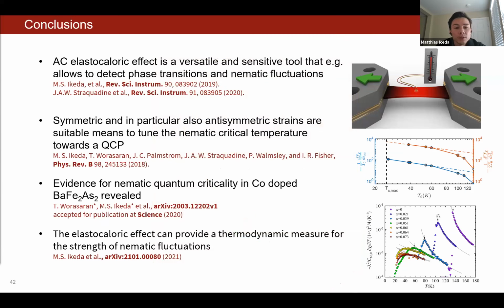And with this, I would like to come to my conclusions and really briefly go through the relevance of our findings. As was mentioned before, in the absence of the coupling of lattice and nematic degrees of freedom, nematic fluctuations are known from theoretical studies to promote superconductivity. But on the other hand, through theory, we also know that coupling to the lattice actually restricts the critical fluctuations. So what we have found is a wide regime governed by quantum critical fluctuations in the system. But we have also found that the coupling of nematic degrees of freedom and the lattice diminishes as we go towards optimally doped regions in the phase diagram. But at the same time, the coupling to the charge carriers increases drastically. And these are all the ingredients needed for nematic fluctuations actually being important for superconductivity. And since I'm out of time, I would now just real quickly leave you with my concluding remarks, and thank you very much for your attention.